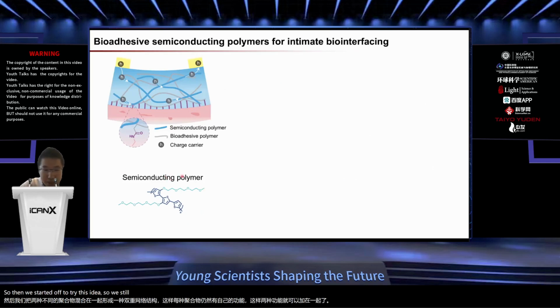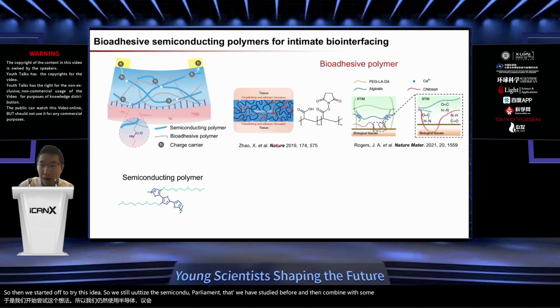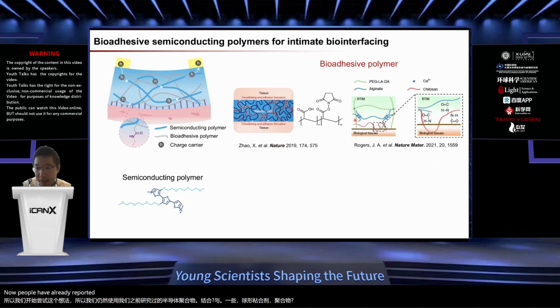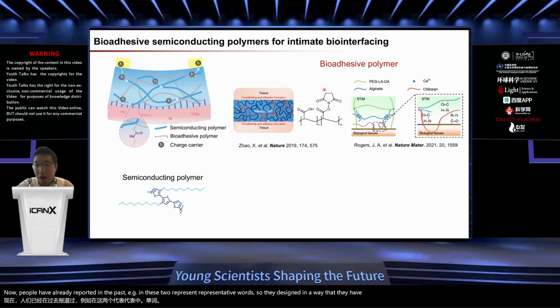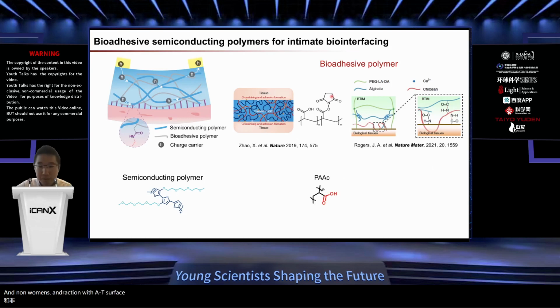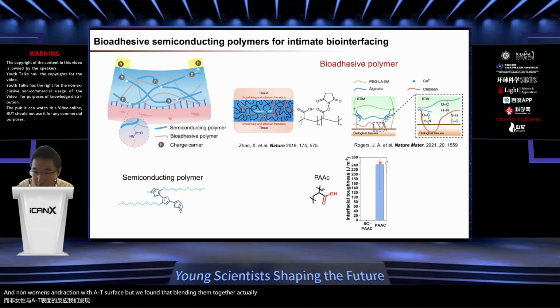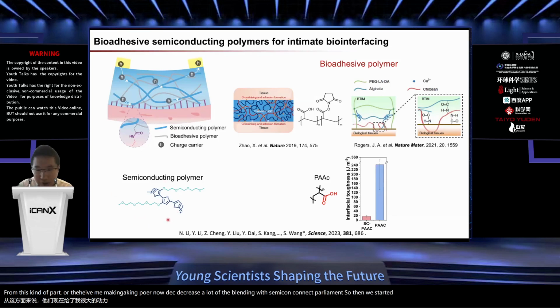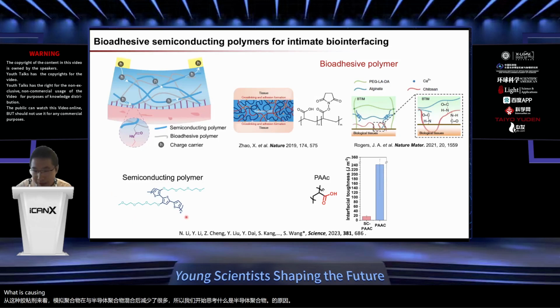We still utilize the semiconducting polymer that we have studied before, and combine it with some bioadhesive polymer that people have already reported in the past. For example, in these two representative works, they are designed in a way that they have bioadhesive groups to form covalent and non-covalent interaction with the tissue surface. But we found that after blending them together, the initially high adhesion from this kind of bioadhesive mimicking polymer now decreases a lot after blending with semiconducting polymer. So we started to think, what is the reason? What is causing this substantial decrease?